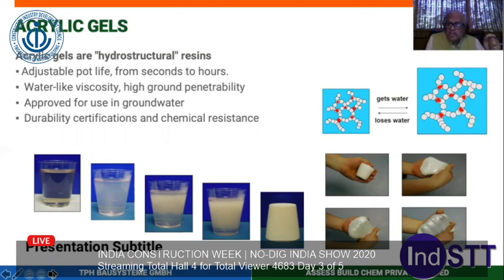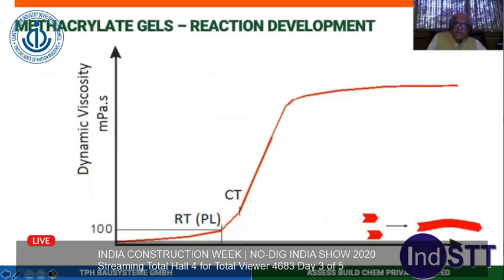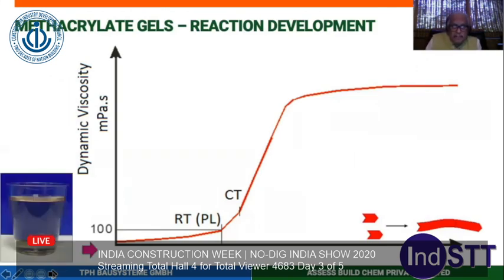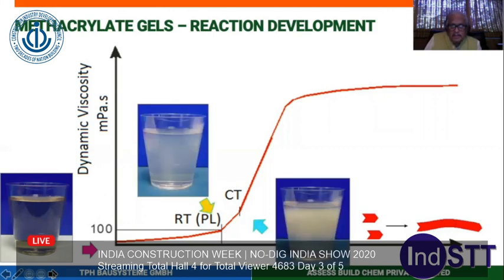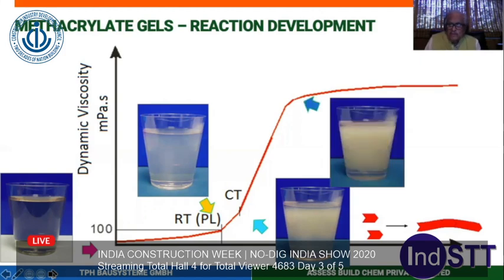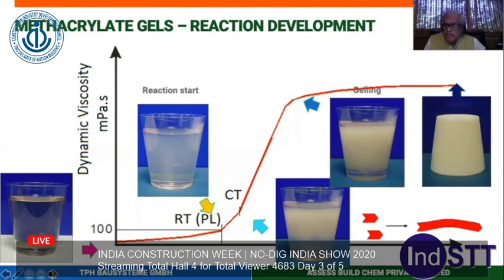Please note, every gel is not a gel. Some gels will just become gels, and after some time they will shrink. Once they shrink, the joint or whatever it is becomes very vulnerable to water entry. So they react very fast. You can see they are having up to, when it reaches say 100 mPa·s viscosity, it is still pumpable. Then the reaction time, in about 10 to 12 seconds, you can control it. Then it starts increasing in the gelation time, and it is gelled. Within about 20 minutes, it is a proper gel.